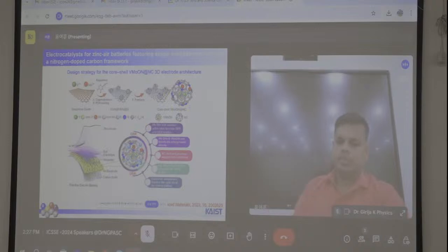You can see the red one is the molybdenum single atom, bonded with the nitrogens, because nitrogen and carbon are bonded. When we are making these core-shell molecules, we do a pyrolysis process. At that time we instantly take a lot of single atoms over the nitrogen-doped carbon shells, and that carbon shell may act as the active sites for energy storage devices like a metal-air battery. The core has vanadium, molybdenum, nitride, which may enhance the conductivity. Then the molybdenum single atom may be helpful as anchoring sites. People know very well that in DFT calculation we have to prove which one is the active site, and when calculating the active sites, molybdenum may be more highly active compared to vanadium, helpful especially for air electrodes. It may be helpful for bifunctional activity, ORR and OER.